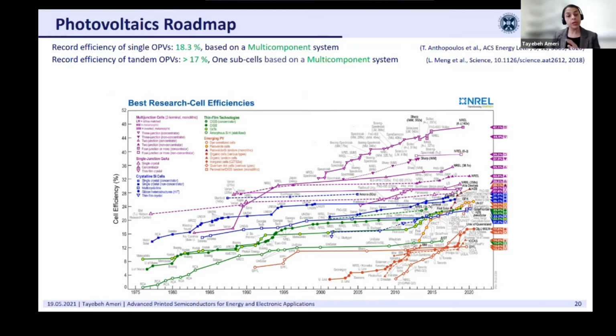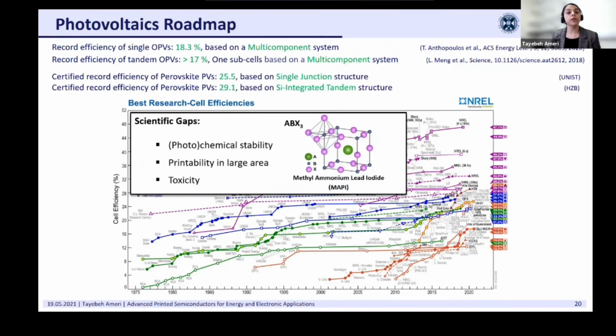So they are doing amazing in terms of performance. However, we still have to address a few key issues to make them commercial. First of all, their poor photochemical stability. The second point is the printability in large area, since it's a polycrystalline material. And for sure, the presence of lead and the toxicity is another issue that has to be addressed.